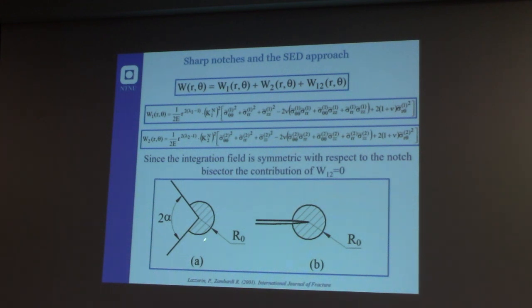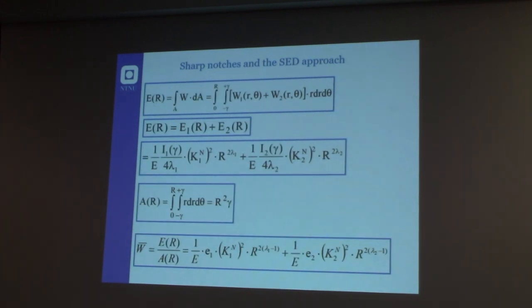But the idea is not to use a stress average in this volume, but a strain energy density instead of the stress for design purposes. Actually, we are merging together a kind of theory of critical distance plus the consideration of a microstructural support length of Neuber. I don't want to give much more explanation, but actually the strain energy density inside the control volume is a function of the stress intensity factor of mode 1 for the notch and the stress intensity factor of mode 2 of the notch, multiplied by the radius r where you are averaging this quantity. So it's a very simple equation, connecting the strain energy density averaged in the control volume to the stress intensity factor that you can measure.